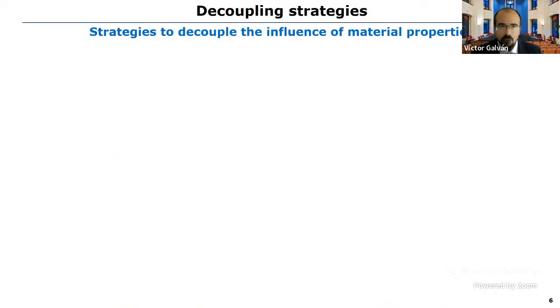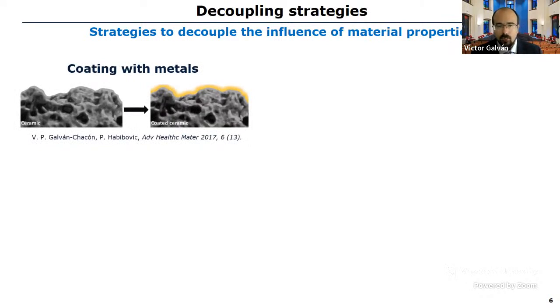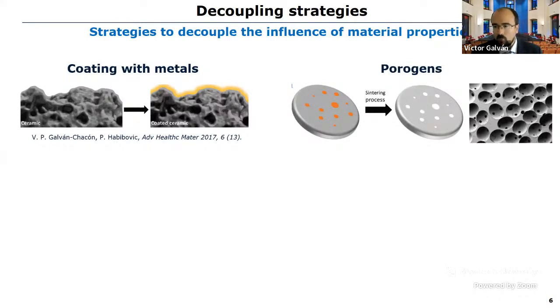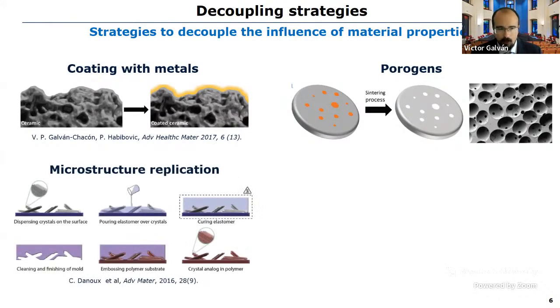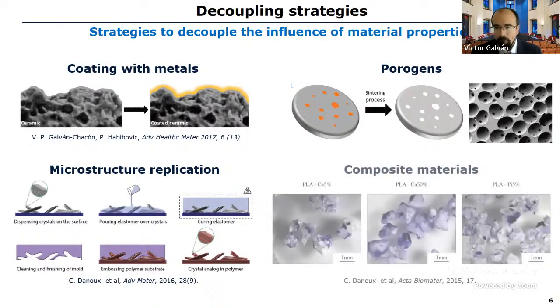So the first thing we did during this thesis was to review what strategies were out there to decouple the influence of material properties. One of them was to coat the ceramics with a thin metal layer, therefore keeping the structural properties but changing the surface chemistry. Also, the use of porogens allowed to introduce pores in a controlled way with controlled size. We can replicate the original structure of the crystals in an analog in polymer, and in that way we also keep the structural properties but with a different chemistry. And we can design composite materials with totally different structural properties, but with some of the chemical cues, like for example, calcium or phosphate salts.